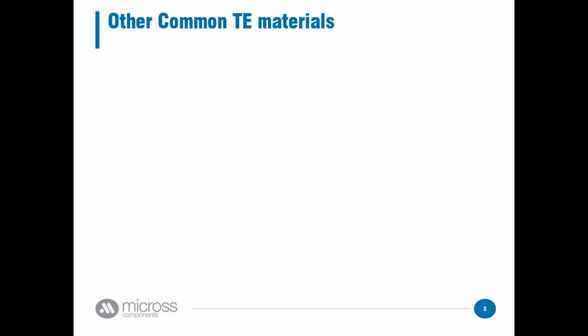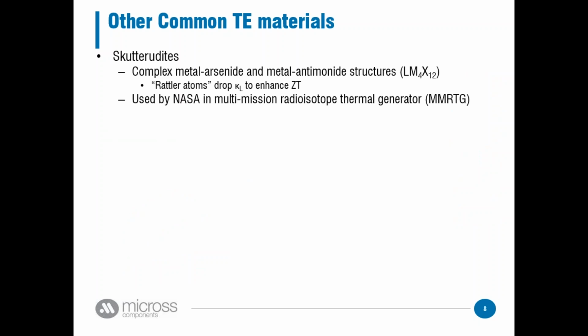Other common thermoelectric materials in addition to the tellurides are skutterudites. Skutterudites are basically like a complex metal arsenide or metal antimonide structure, which essentially has what's called a rattler atom. It's a hollow structure that has some type of large, usually a rare earth atom inside of it. That rare earth atom is going to rattle, shake around in that lattice at a different frequency than the actual structure of the material itself. And that disconnect, that disharmony, manages to scatter the thermal conductivity, which means you have the lower thermal conductivity you need to have a good thermoelectric effect.